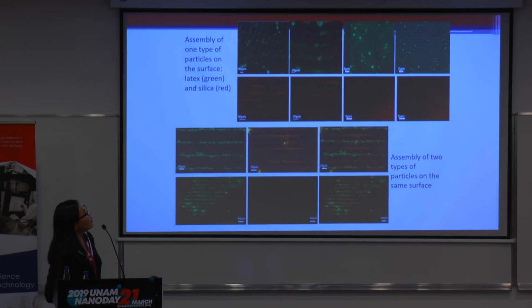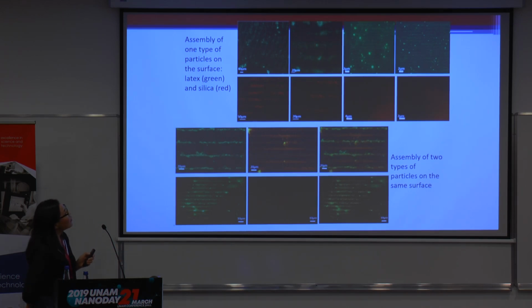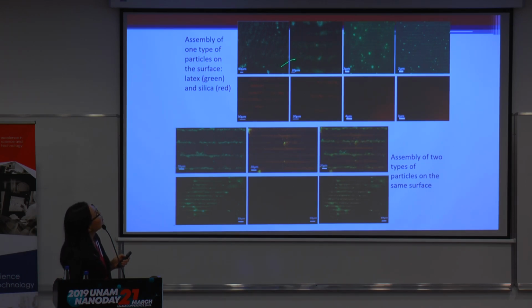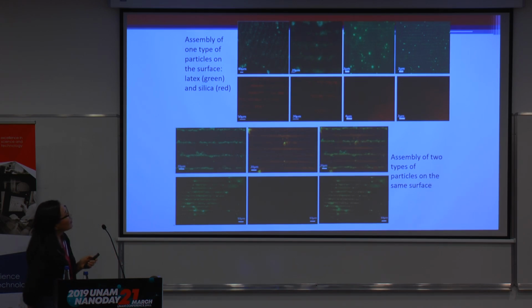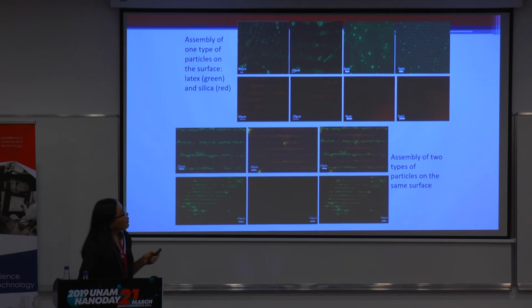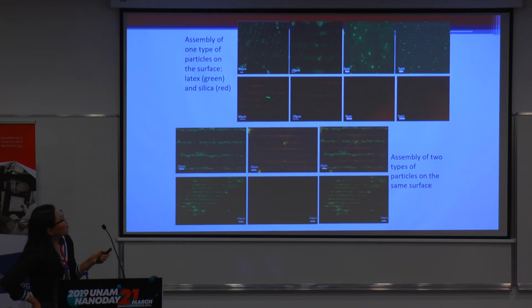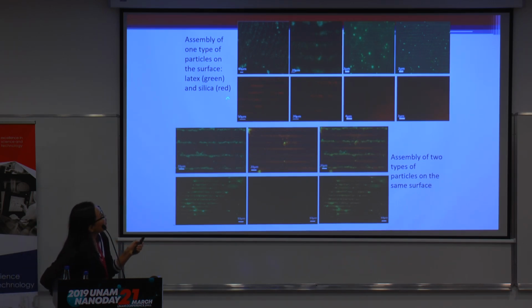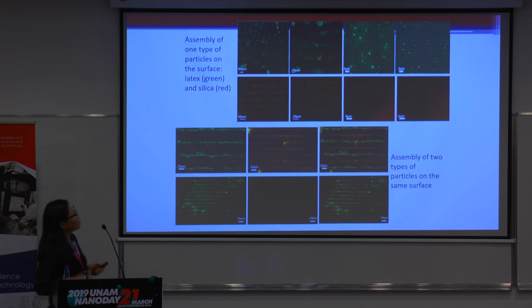In the first part of this study, we obtained patterns of one type of particles. So in this case, these are fluorescent green latex and fluorescent red silica particles. And the particles are deposited only on the surfaces of the electrodes, and the gaps between them are empty because these are insulating areas. And so the second part of the project was obtaining, as I mentioned, multifunctional surface.